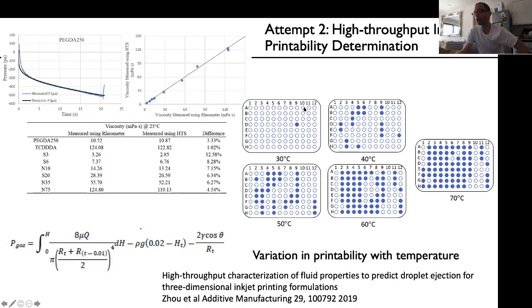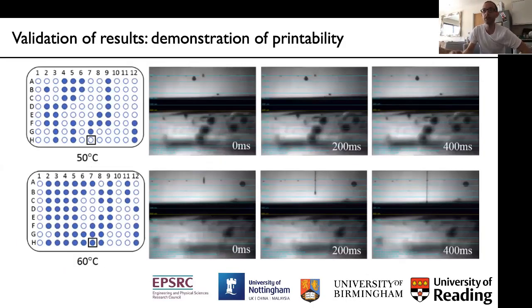And so just as a quick test, we took a whole bunch of materials that really weren't printable at a low temperature, room temperature, and we increase the temperature, the viscosity comes down, and you can see that the printability gets better and better as we increase the temperature, in line with what we would expect. And then we did our sort of litmus test. We took a material that we predicted to be not printable at 50 degrees. That's the material that's labeled on this screen, and the same material would be printable at 60 degrees. And we tested that on our printers.